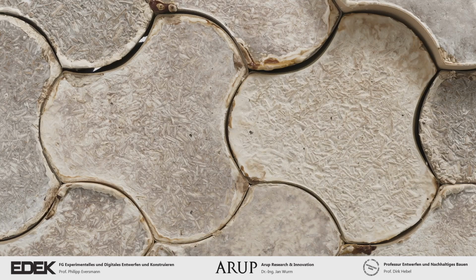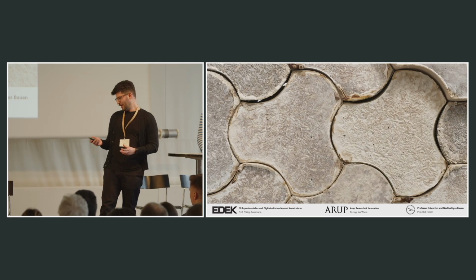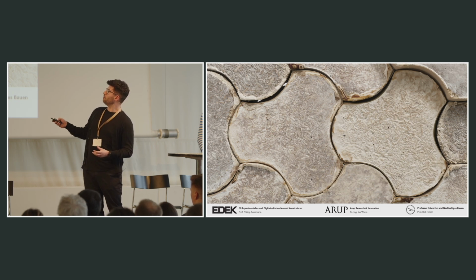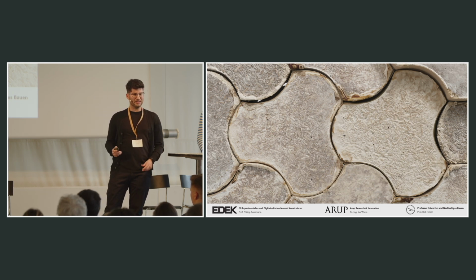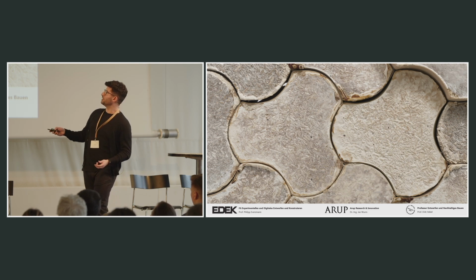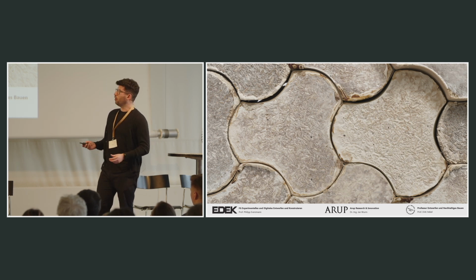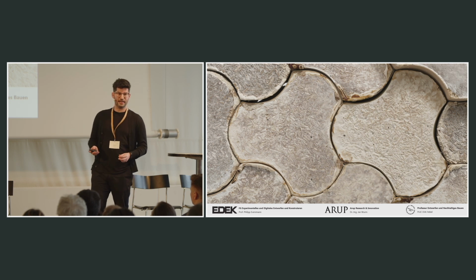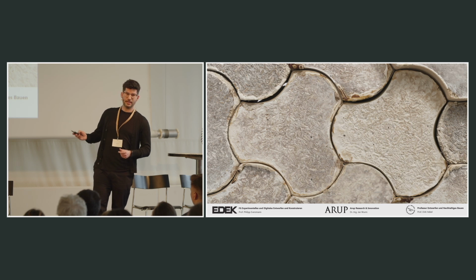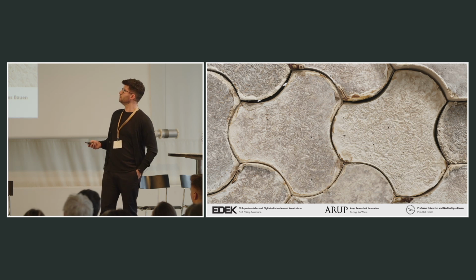Unfortunately, or actually fortunately partly, we had a very strong bond created between the outer shell and the mycelium composite. That means that despite its stability, we still got a certain amount of shrinkage happening, and also due to the fact that we have several people filling the blocks and everybody had a different idea what a filled block means, we end up with a certain level of non-uniform shrinkage. However, what we could do is tune the interlocking detail in order to ensure that despite the shrinkage that we could expect, the interlocking would still work and would still transfer the loads.